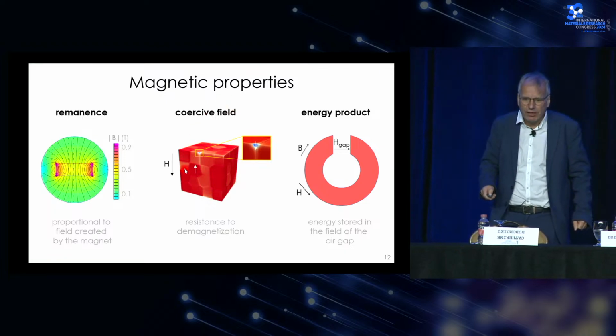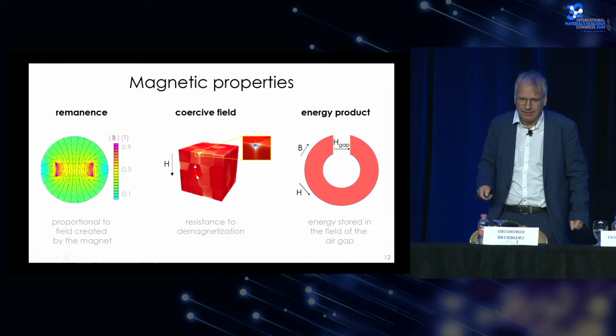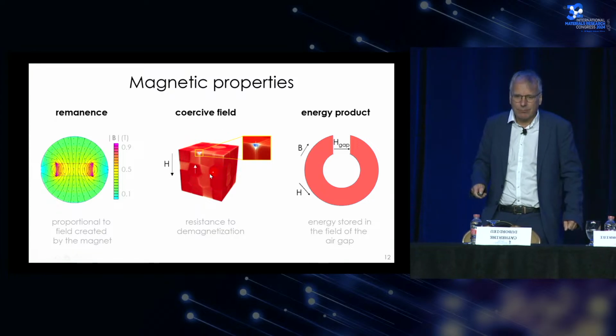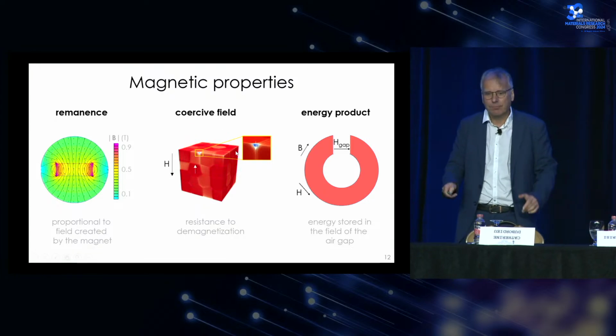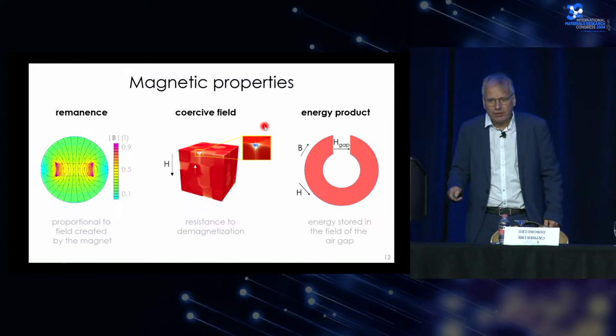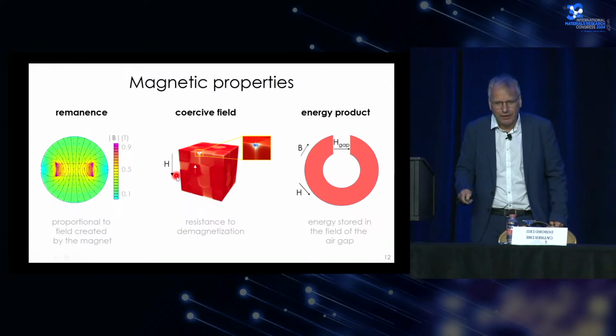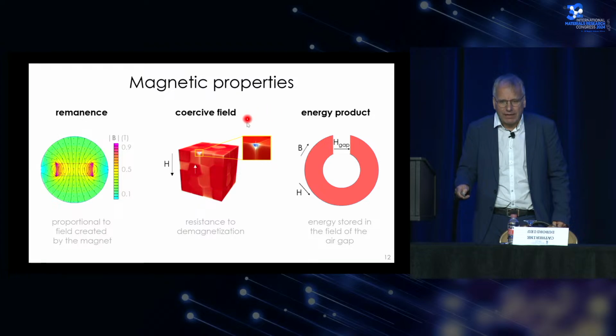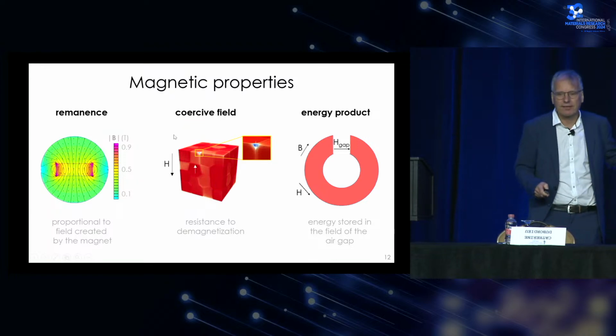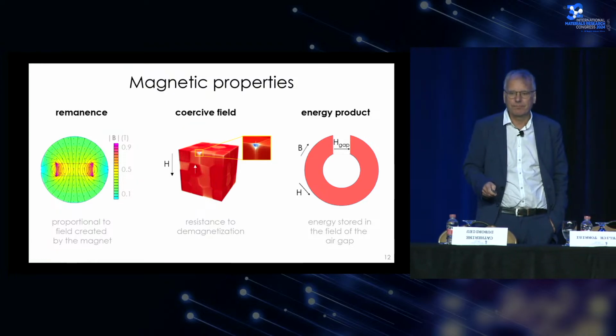And if we do simulations, we see that all the magnetic moments point up, indicated by the red color, but at certain points, if the external field is strong enough, the magnet can become demagnetized. As you can see here, it's typically happening at edges, corners, and grain boundary faces.